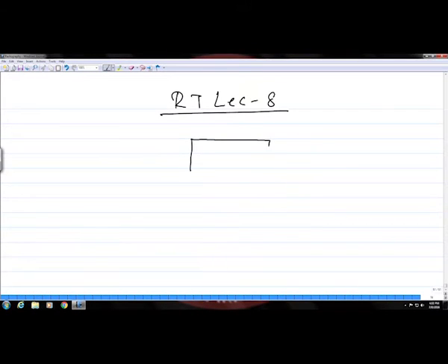Another kind of casting defect which can lie inside the volume of the cast component is non-metallic inclusions. For example, if you do sand casting, many times a sand particle can go inside the casting, and that will be a defect as far as the quality of the casting is concerned. So, let us say you have a non-metallic inclusion like this inside the casting, which is exposed to X-rays,